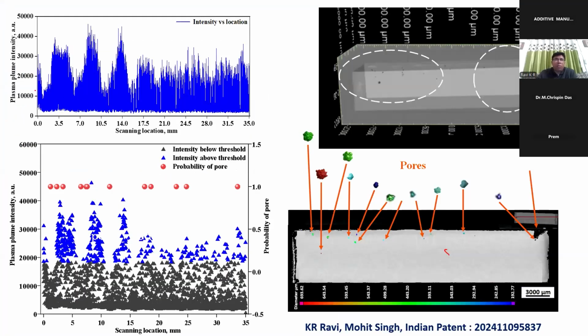When we work in the keyhole regime, we identify certain sinusoidal peaks forming. Each of these corresponds to a keyhole collapse. We could see that porosities were forming in that region. These are the regions where we identified the probability of pore formation, and there is experimentally observed porosity in a similar location.